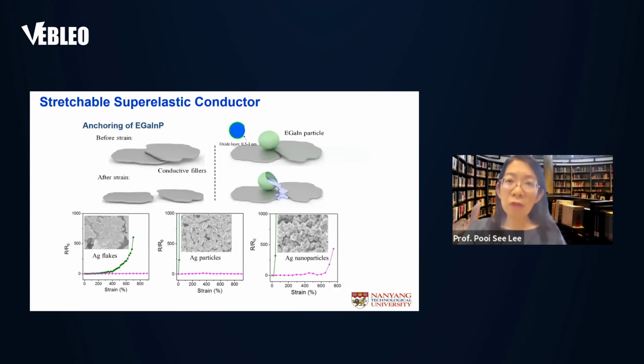So we thought of the hypothesis of adding a liquid metal which can serve as anchoring particles between the silver flakes, so that upon stretching, these liquid metal particles, which have an encapsulating oxide shell, could be broken and release the conductive liquid metal to mitigate the increase in the resistance. Indeed, this works very well.